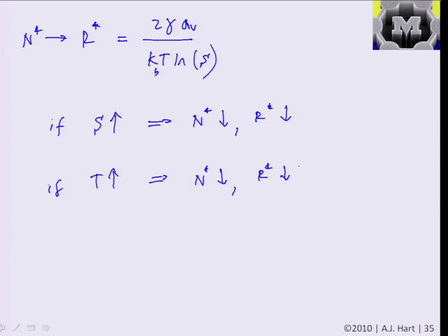And ideally what we want to do, going back to the first picture, is start the process by adding that precursor and rapidly increasing the temperature. And then once we form the nuclei, we want to step back into a regime where we already have clusters that are above the critical size, so they're not going to dissolve, but they still want to grow to decrease their free energy. And next time we're going to see the next picture of the process.